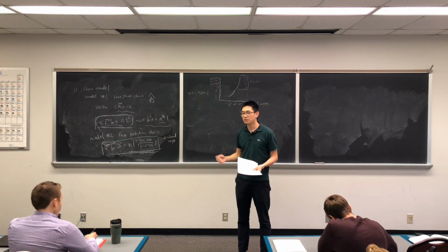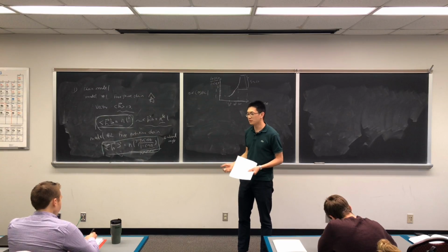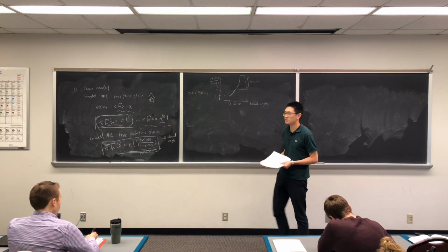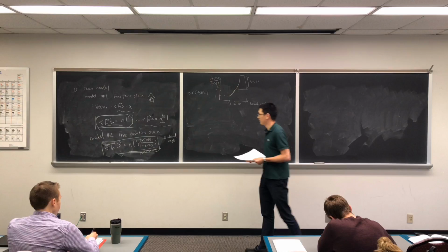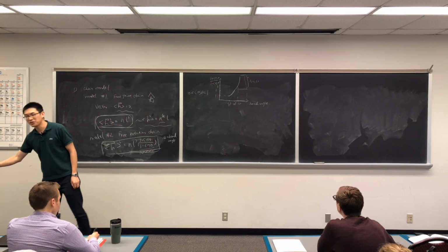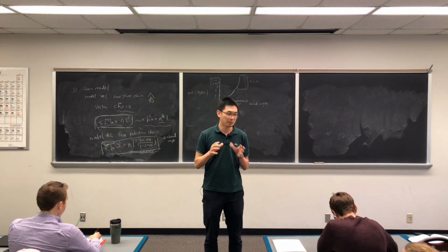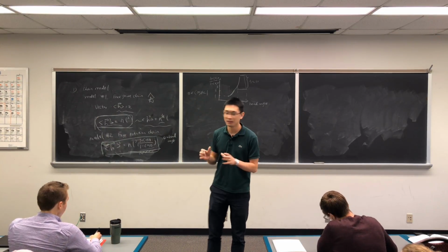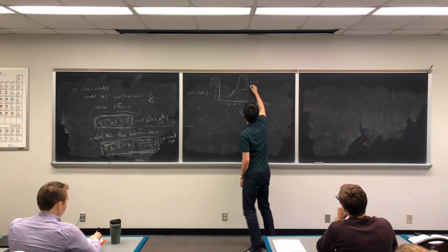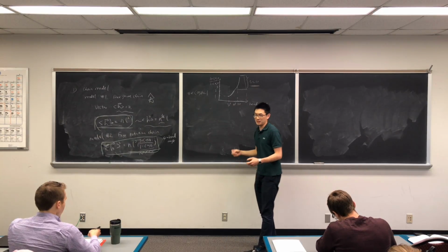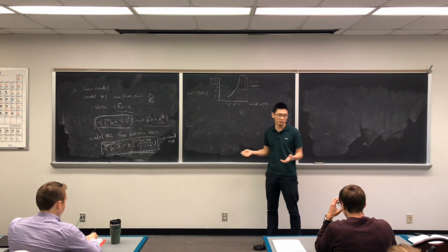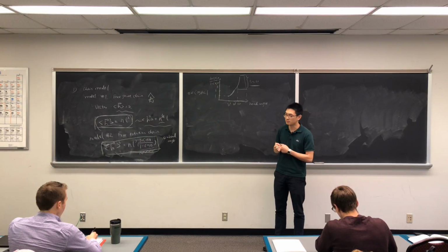So in other words, if you consider the bond angle, the difference is going to exist between the free joint chain and free rotation chain. And this factor depends on specific bond angle. This value is somewhere between 3 to 10, where you mostly will encounter in most of the flexible polymer.